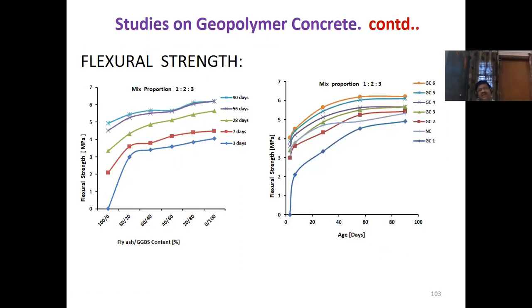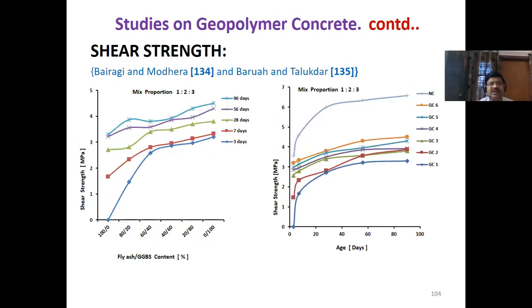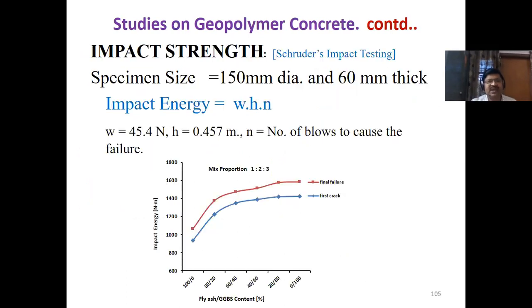Flexural strength also we conduct using the beam. You can see here it's around 6 MPa. So that means the same trend whatever we have observed in normal concrete appears in the case of geopolymer concrete also, right? Next, shear strength, right? This is also around 4 MPa. So compressive strength, split tensile strength, shear strength. Next, impact.